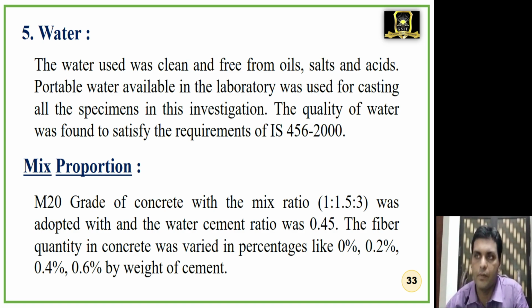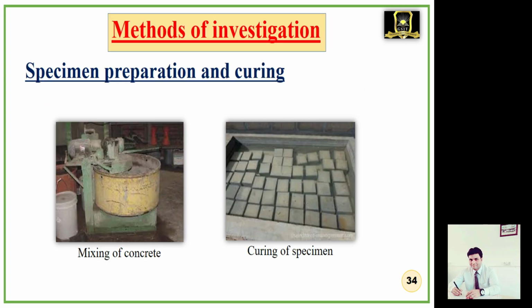Mix proportion: M20 grade of concrete with mix proportion 1:1.5:3 and water cement ratio 0.45 was used in this experiment. The fiber quantity in concrete was varied in percentages like 0%, 0.2%, 0.4%, and 0.6% by weight of cement.